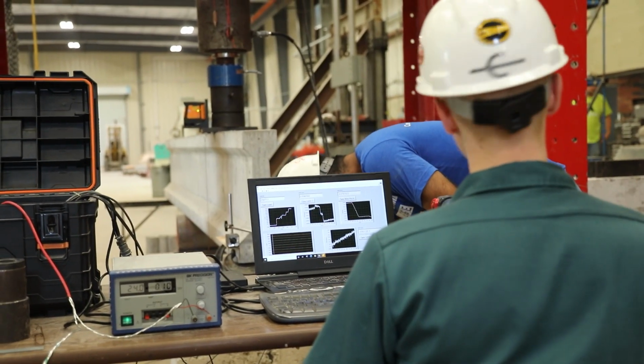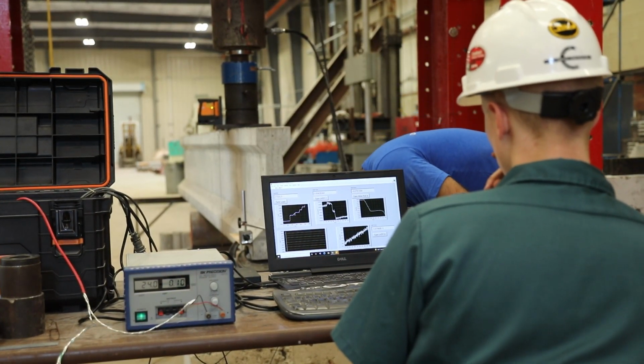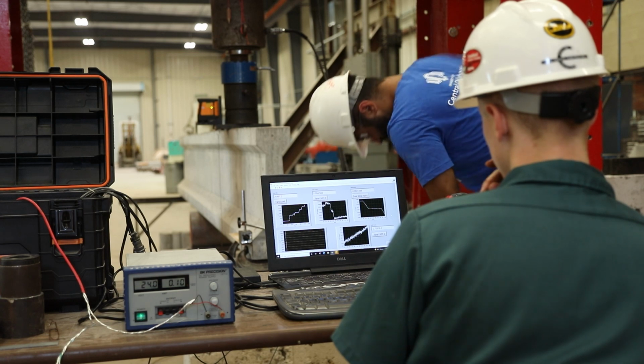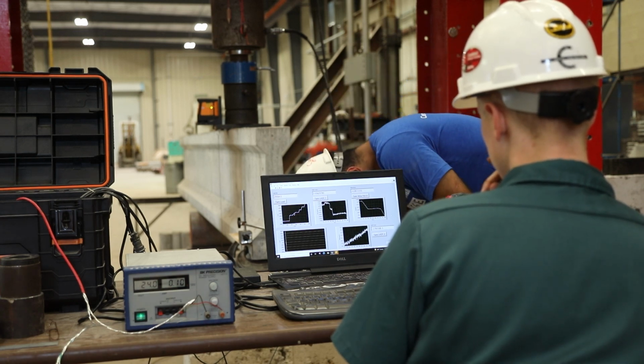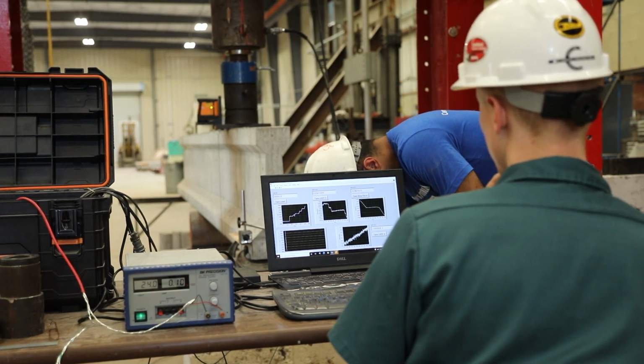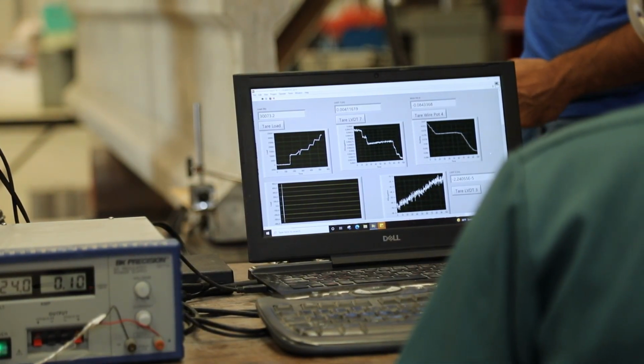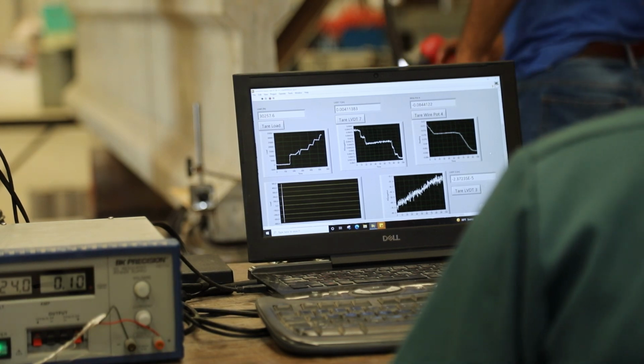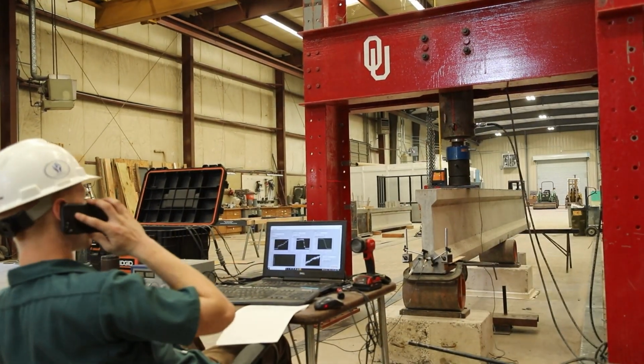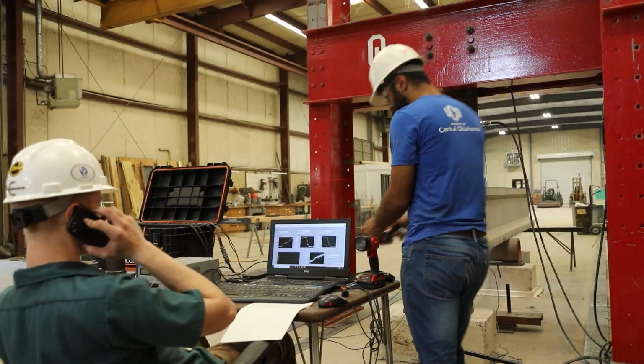And you said that the corrosion actually adds some strength, at least on the front end, right? But on the back end of that, there's a different issue. There's a lot going on there, especially when we're corroding reinforcement that's under tension, like in these pre-stressed beams. But for the specific failure mode that we were examining, which is shear in the end region of the beams, it's often controlled by the strands pulling out of the concrete. So the strands have to be anchored into the concrete to act as a composite, to work together to resist the loads. And by loads, for a bridge, that would be the trucks going over it.